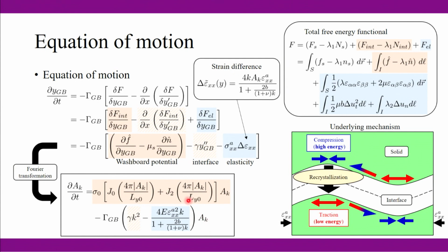So this actually captured that, right? You see there's a suppression or stabilizing force proportional to k squared, and the prefactor is associated with the physical quantity, the surface energy. And second part is from the elasticity, but you have some modification in the denominator that's associated with our soft boundary, soft property of the interface.